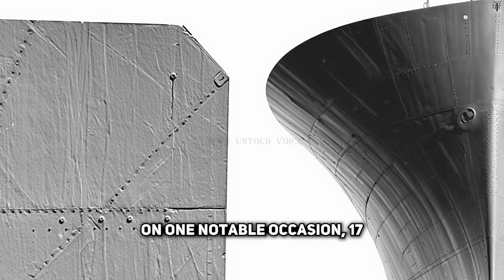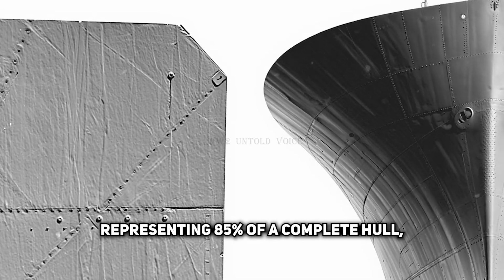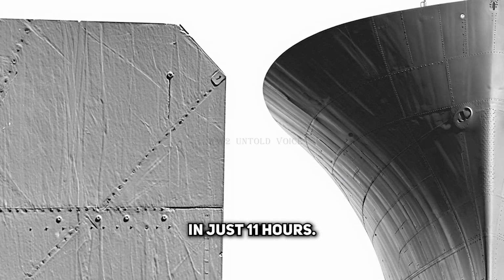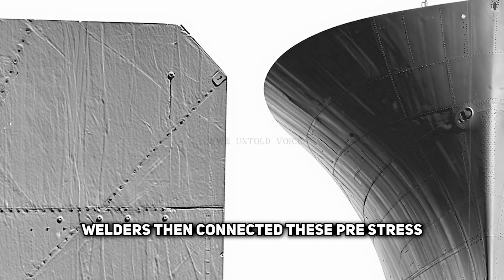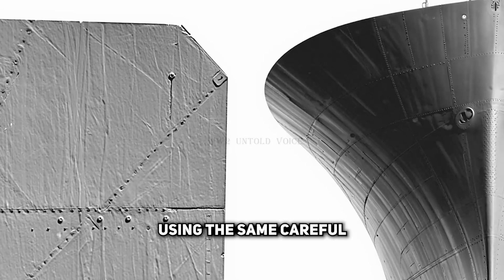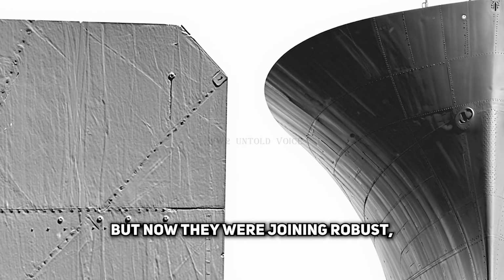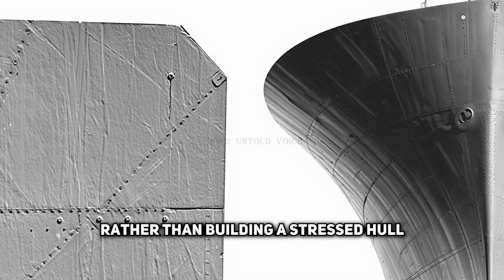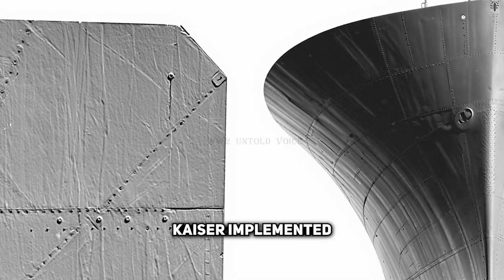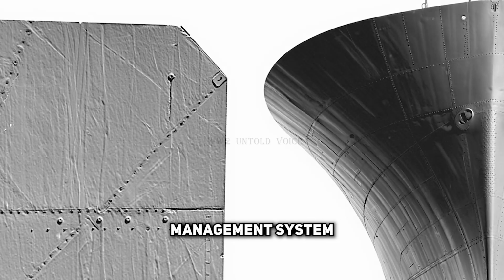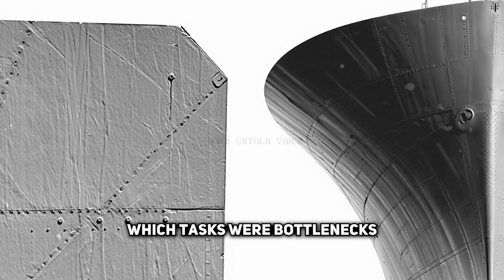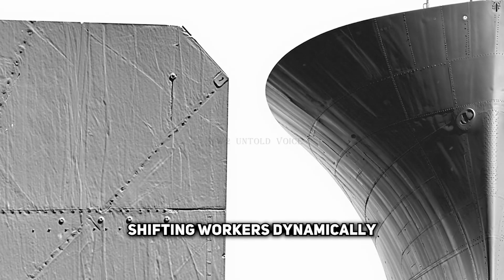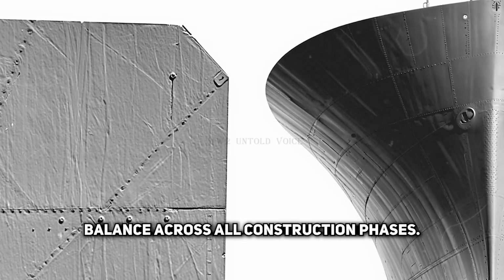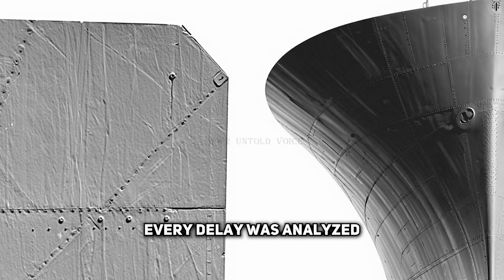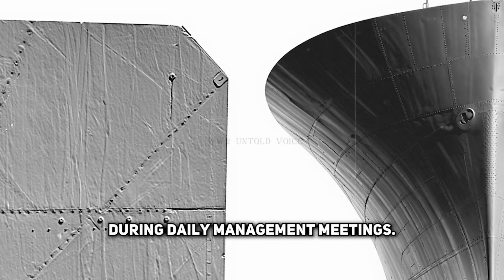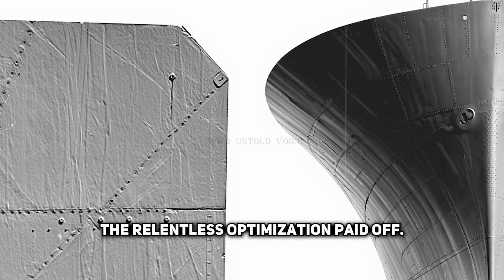On one notable occasion, 17 major modules, representing 85% of a complete hull, were aligned and set in place in just 11 hours. Welders then connected these pre-stress relieved modules using the same careful sequencing principles, but now they were joining robust, stable components rather than building a stressed hull from scratch. Kaiser implemented a sophisticated, critical path management system, constantly tracking which tasks were bottlenecks and which could be accelerated, shifting workers dynamically to maintain perfect balance across all construction phases. Every delay was analyzed and solutions were implemented in real time during daily management meetings. The relentless optimization paid off.